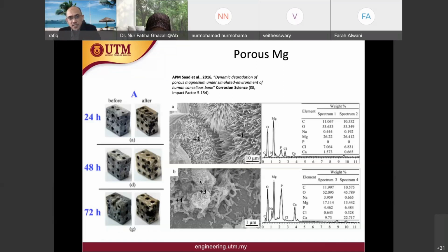But the problem is, of course, magnesium is easily corroded. Easily corroded. So we analyzed the dynamic degradation of porous magnesium under a simulated environment of human cancellous bone, and we managed to publish it in Corrosion Science, one of the top journals in this particular field. Again, what we analyzed is a simplified cancellous bone. We take a magnesium block and we create holes, and then we analyze the corrosion aspect of this porous magnesium after 24 hours, after 48 hours, and after 72 hours, and you can see that it's corroded there.